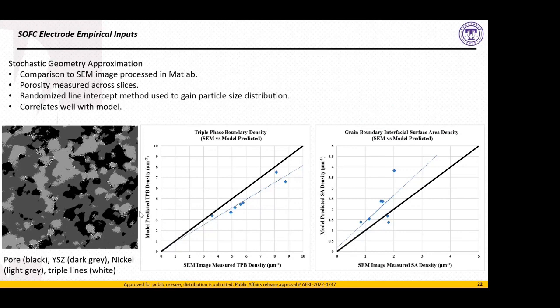Now, we want to compare our model and our assumption of spherical packings and percolated spherical microstructures to images that we have. So we did a comparison of our stochastic geometric approximation, compared that to SEM images that we processed in MATLAB, and again measured the porosity across the slices, and used the randomized line intercept method to discern the particle size distribution.